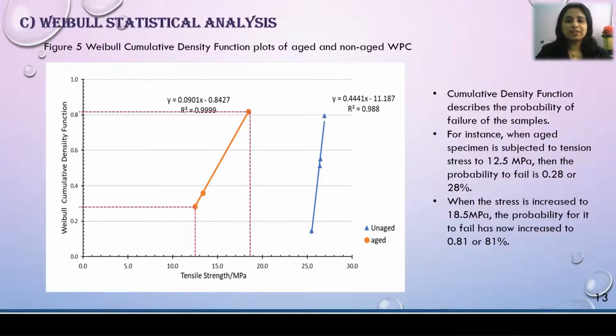Lastly, the cumulative density function describes the probability of failure of the samples. From the graph, it is found that when the aged specimen is subjected to a tensile stress of 12.5 megapascal, the probability for the specimen to fail is 0.28 or 28%. And when the stress is increased to 18.5 megapascal, the probability for it to fail has now increased to 0.81 or 81%.